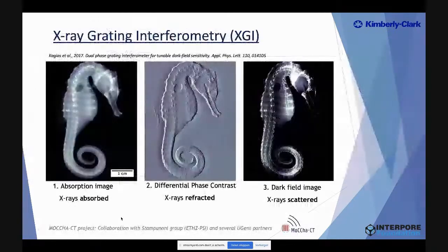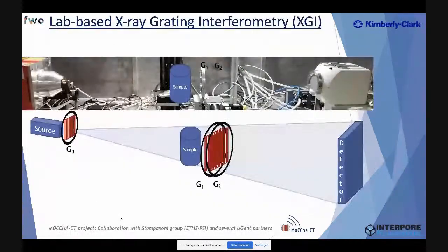One of the things that we are therefore currently doing is experiments with X-ray grating interferometry, in collaboration with the research group of Marco Stampanoni at PSI ETH and several Ghent partners. What we try to do with tunable gratings is to retrieve the dark field image in order to obtain information of sub-resolution features of our sample. So how does such a setup look like?